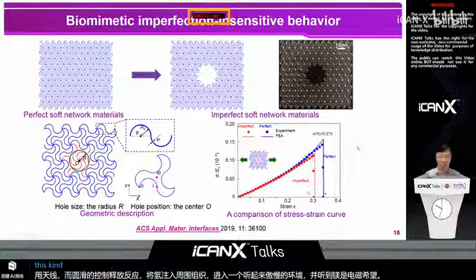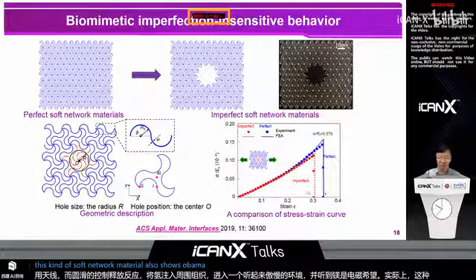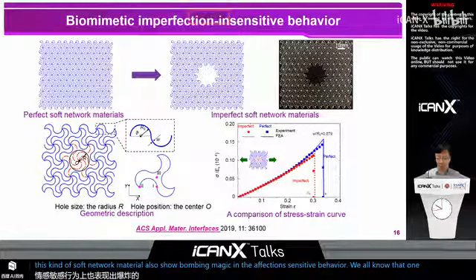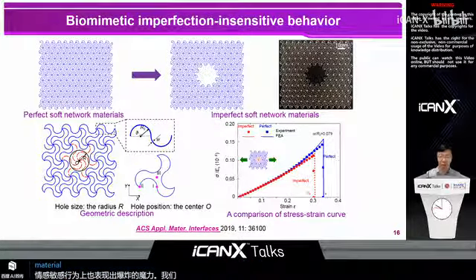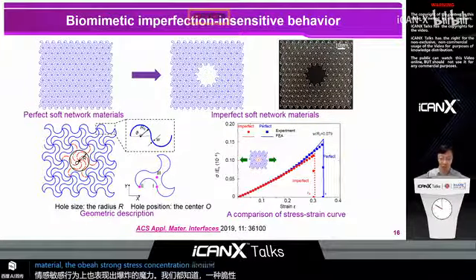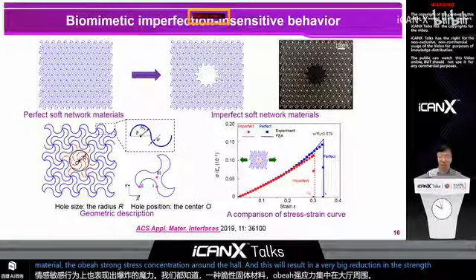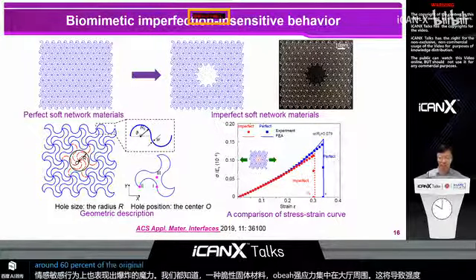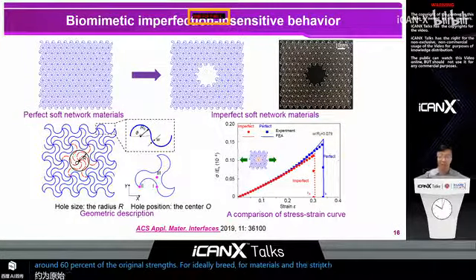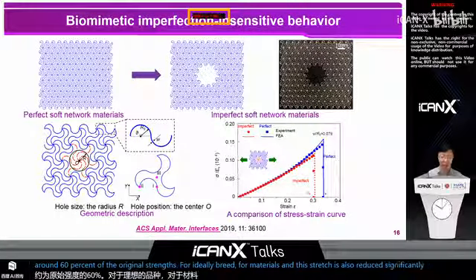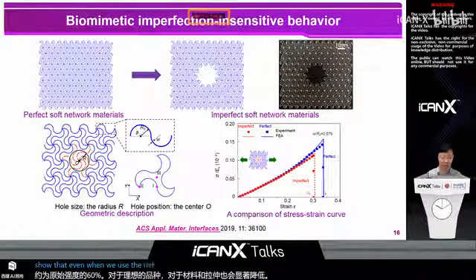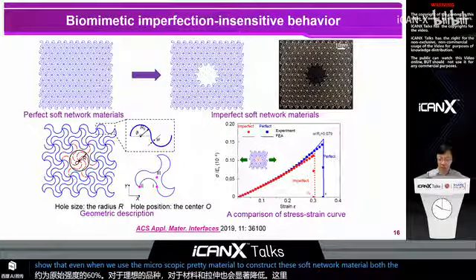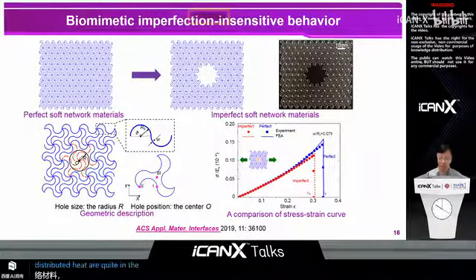Actually, this kind of soft network material also shows biomimetic imperfection insensitive behavior. We all know that with a brittle solid material, there will be a strong stress concentration around a hole. This will result in a very big reduction in strength, typically around 60% of the original strength for ideally brittle materials, and the stretchability is also reduced significantly. Here we show that even when we use a macroscopically brittle material to construct this soft network material, both the strength and the stretchability are quite imperfection insensitive.